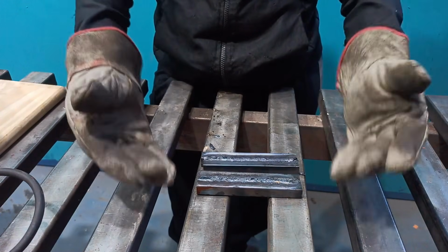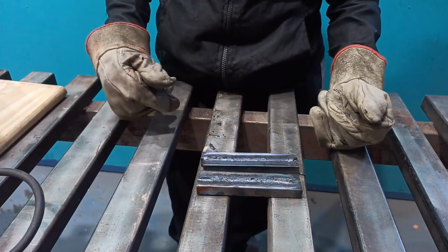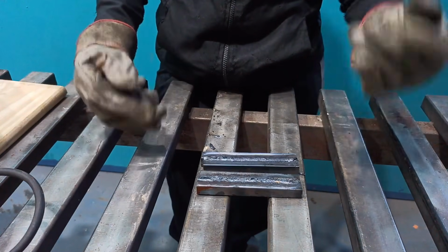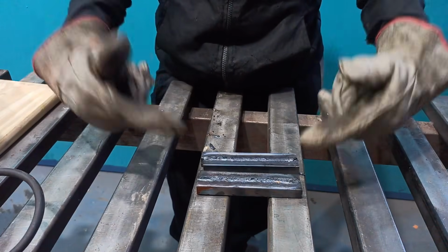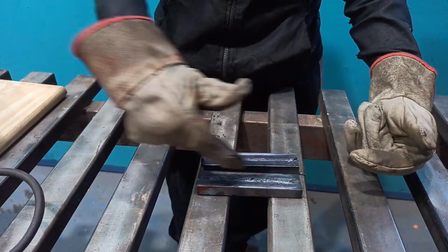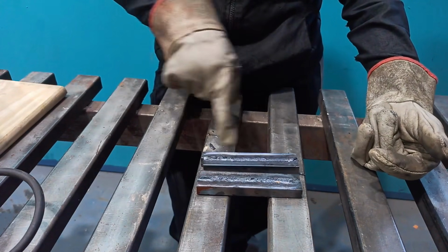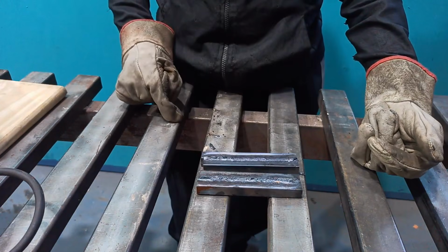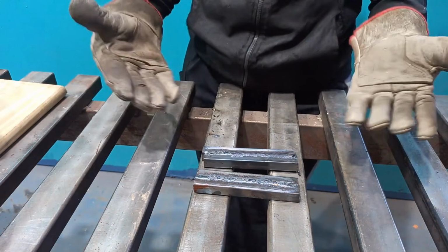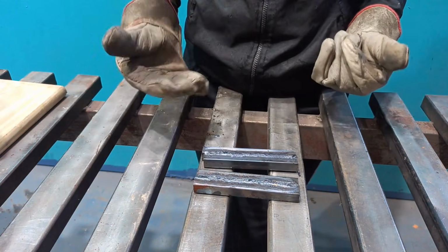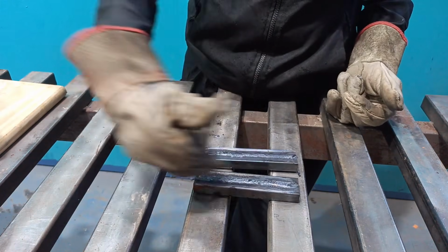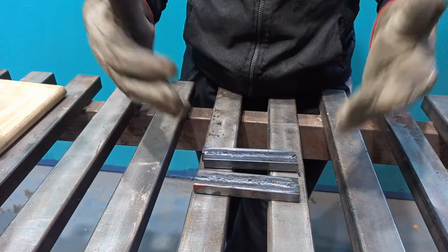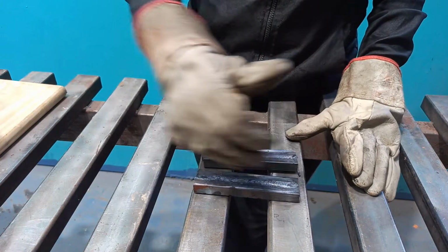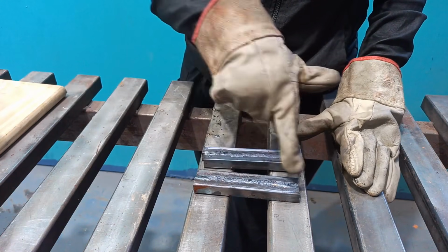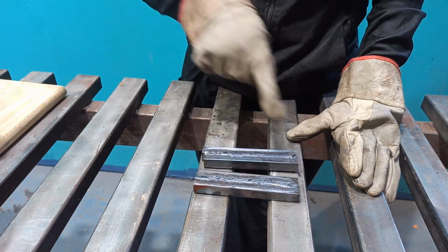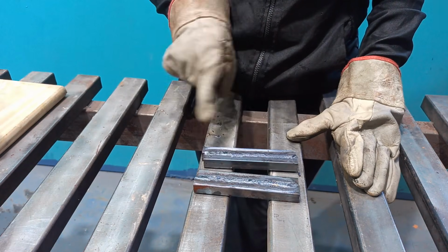Here I already have both of them welded. I welded one with straight polarity and the other with reverse polarity. I welded this one with straight polarity and this one with reverse polarity. One of the differences you can see at first glance is the slag. For example, with straight polarity, the slag is harder to remove. And with reverse polarity, it comes off by itself.